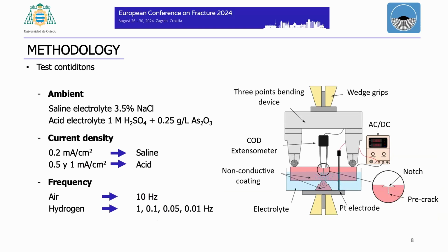Regarding the test conditions, we evaluate two different ambients as we're using two different electrolytes. A saline electrolyte, 3.5% of sodium chloride, and an acid one, which is more aggressive. That is a solution of sulfuric acid and arsenic oxide. We use different current densities, 0.2 for the saline electrolyte and 0.5 and 1 for the acid electrolyte.